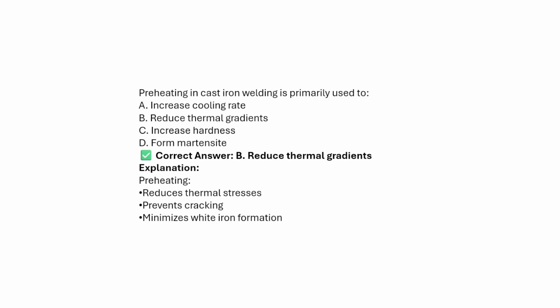Preheating in cast iron welding is primarily used to increase the cooling rate, reduce the thermal gradients, increase the hardness, or form martensite. The answer will be: preheating to reduce the thermal gradient. Preheating reduces the thermal stresses, prevents cracking, and minimizes the white iron formation.